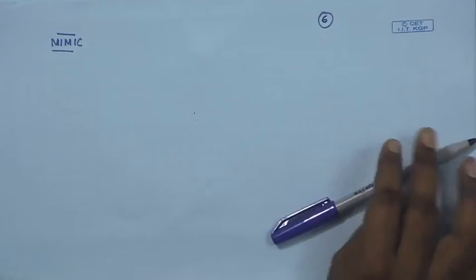So, what you tend to realize is that a couple of major problems of nano imprint lithography are, you are using a rigid stamp, therefore stamp release is a problem, and also you are trying to pattern a very high viscosity layer, a molten or a softened polymer film, straight away. So, the viscous stresses, firstly you need a high force to do the deformation, and secondly it also leads to a very high level of residual stresses.